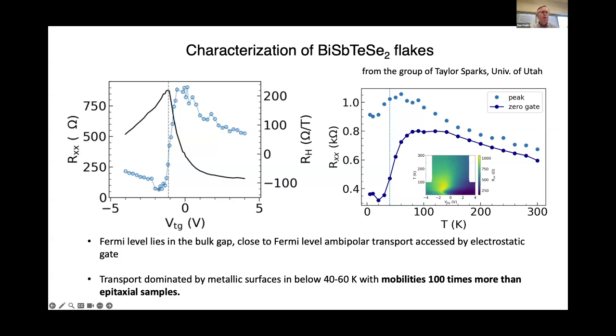You can test the quality by making sure that the Hall resistance without any magnet nearby changes sign near 0 top gate voltage, and the longitudinal resistivity also shows fairly sharp peaks, indicating high mobility.